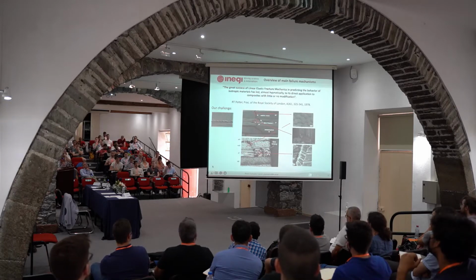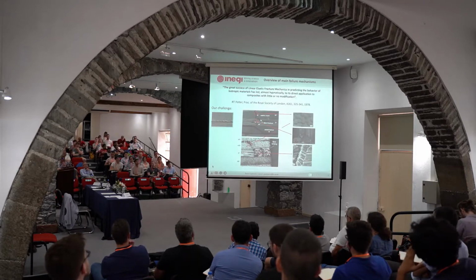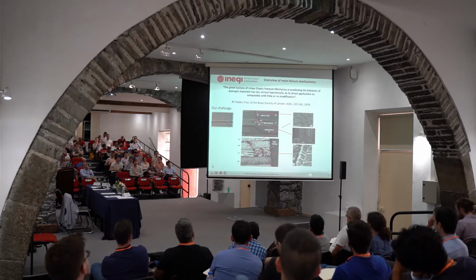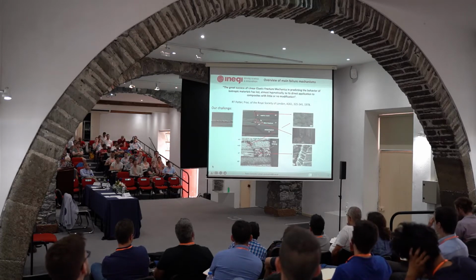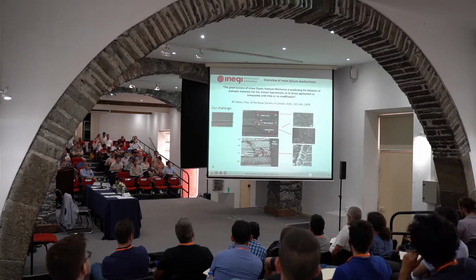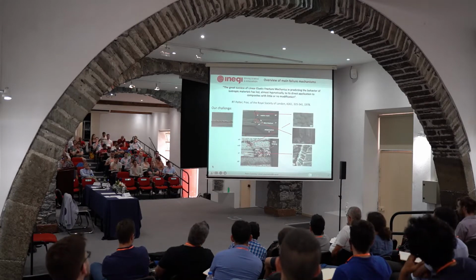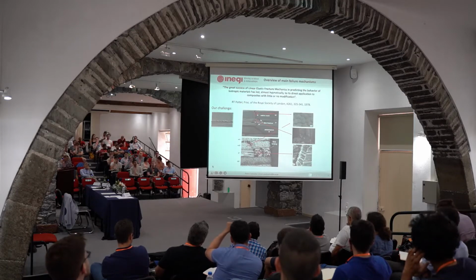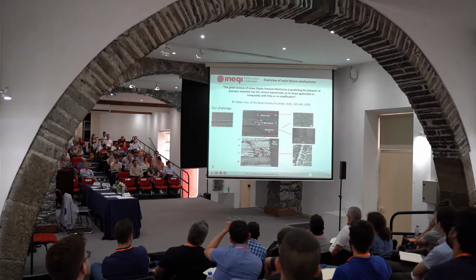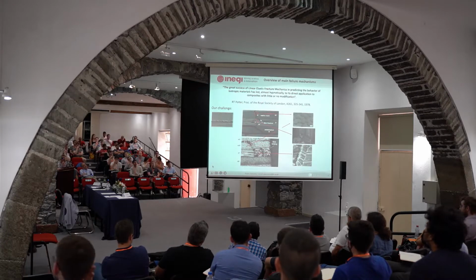Yeah. You can see the picture. Okay, so these are the longitudinal cracks there and there, and these are the transverse cracks. Okay, so with different orientations. And then if we zoom in more detail, you can see here that these transverse cracks correspond to fiber matrix debonding and then cracks propagate through the matrix. Whereas when we have the longitudinal failure, like here, you can see that we have failure of all the constituents. So you can see broken fibers, the matrix is also broken, you have fiber matrix decohesion, and if you apply compression, then you can see these very complex kink bands that Professor Soutis studied in his PhD some time ago, right?